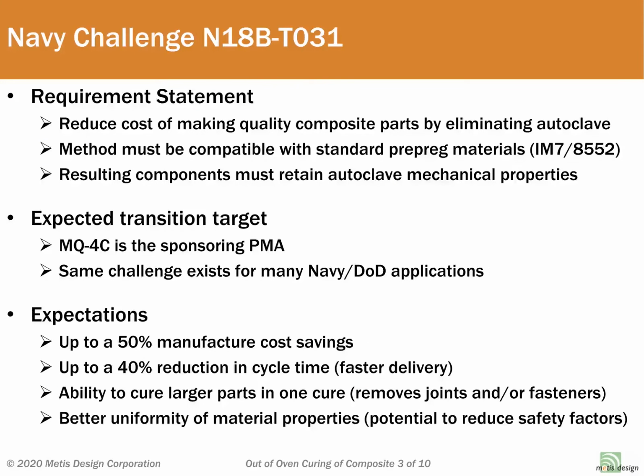Simply put, the goal for this STTR program was to reduce the cost of making quality composite parts by eliminating the use of an autoclave. This must be accomplished using a method that's compatible with standard autoclave prepreg materials, such as IM7/8552, commonly used by NavAir, and the resulting components must retain mechanical properties that are typically achieved when using an autoclave to cure.